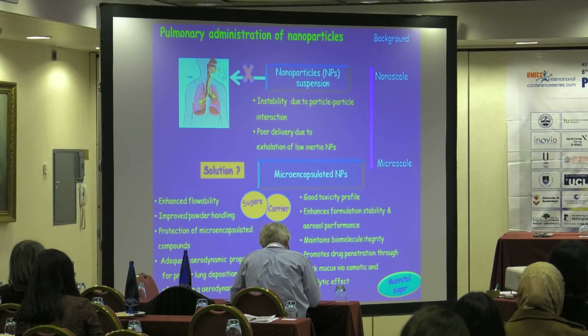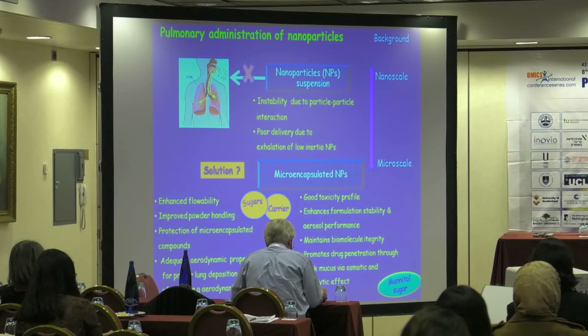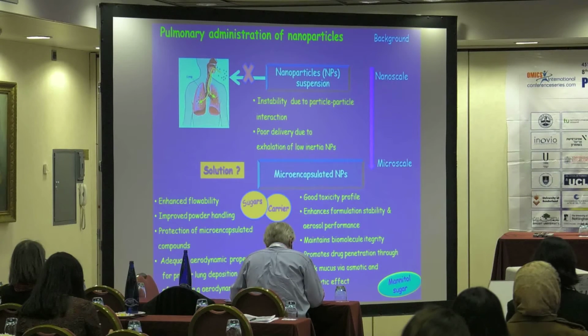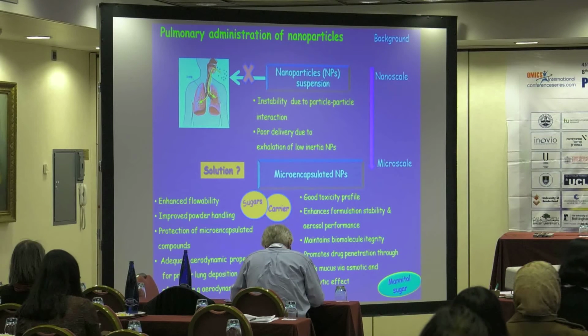We found that mannitol maintains biomolecule integrity upon spray drying, and also improves or promotes drug penetration through thick mucus via osmotic and mucolytic effects. So we used mannitol for spray drying, or microencapsulation of the nanoparticles.